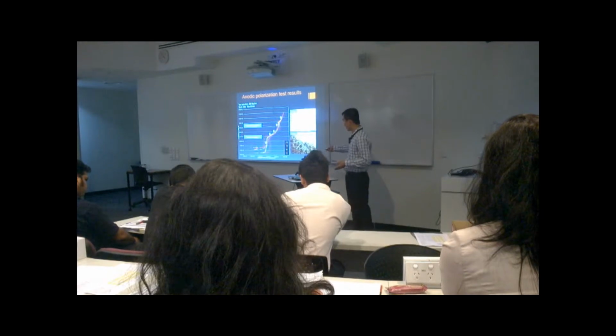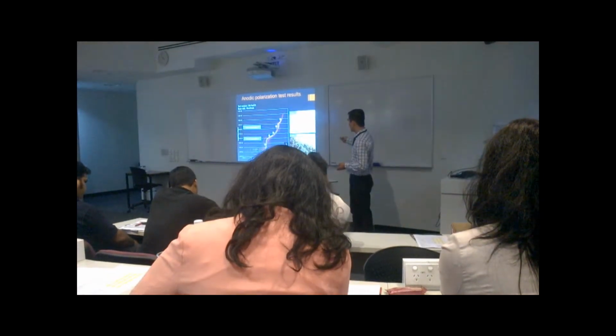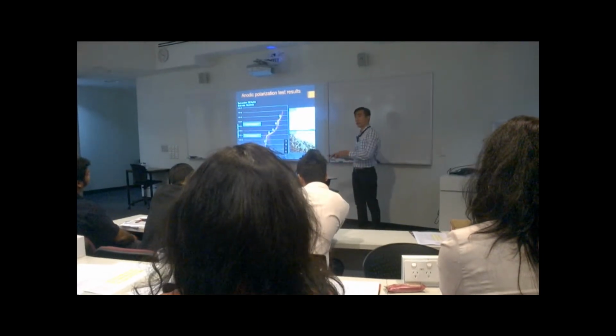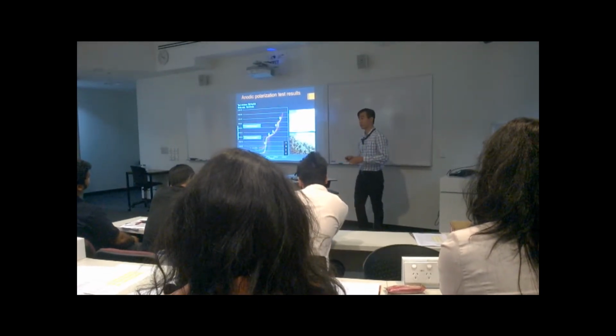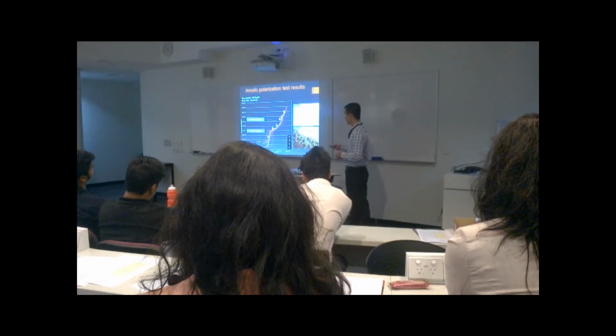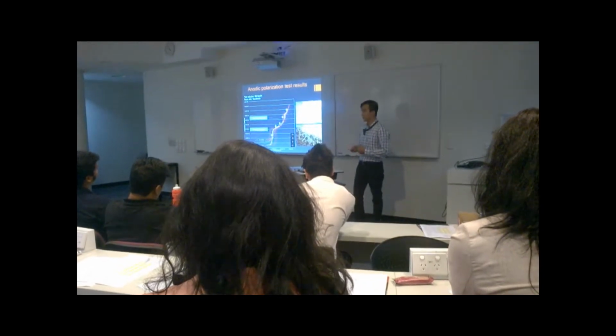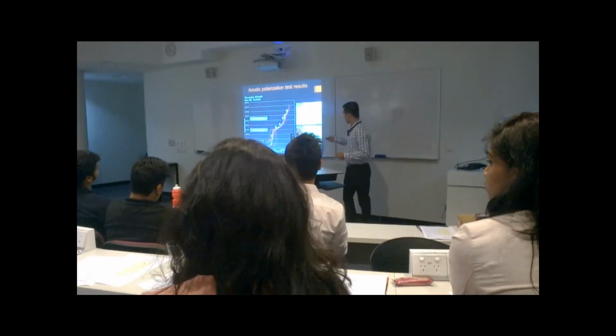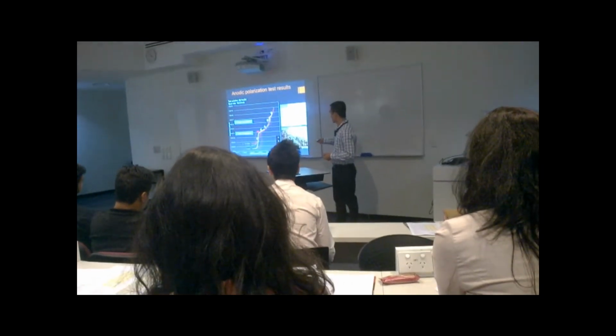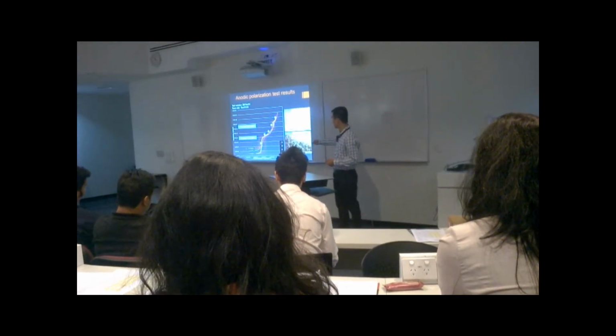So unfortunately, not as I expected, all the curves are similar in this solution of high pH. It means that the corrosion behavior of different alloys, different microstructures, and chemical compositions are the same. So the corrosion behavior of them are the same in these solutions. However, there are 2 important findings that I found from the test. The first one is they form 2 passive layers. The first one is here, the second one is here.